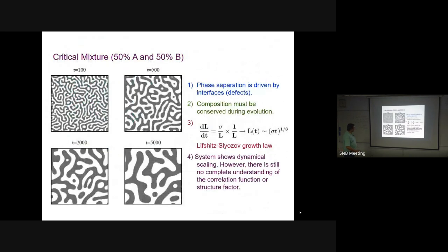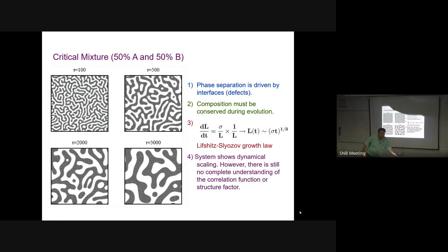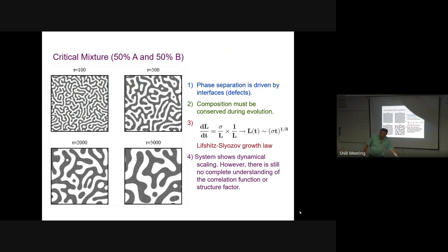Unlike the non-conserved case where we have a good approximate theory (OJK), for the conserved case we don't have a good analytical handle on the full scaling function. The reason is: in the non-conserved case an interface moves locally based on its curvature. In the conserved case, if one interface moves, all other interfaces must readjust to conserve composition. This is a much harder problem which has not been fully solved.